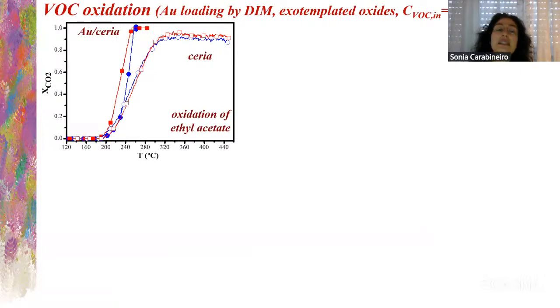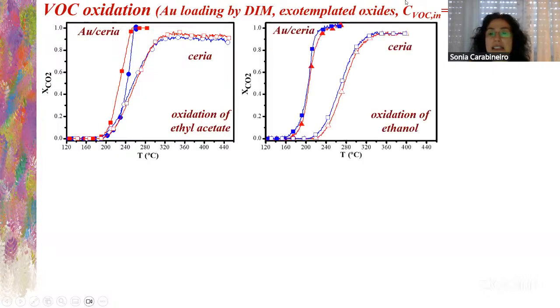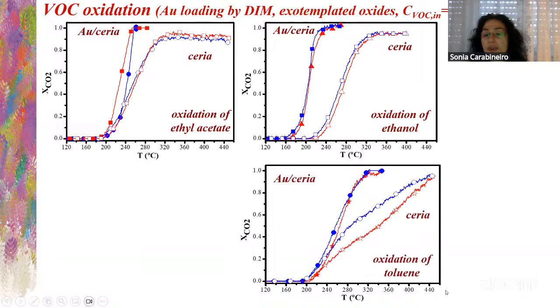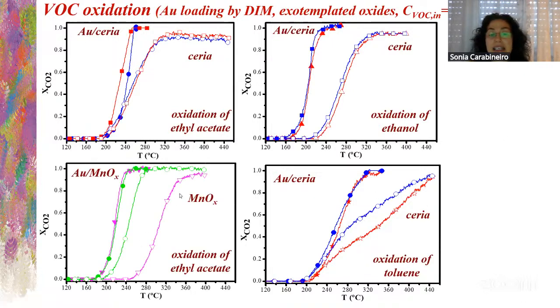And finally, with VOC oxidation using gold, okay, materials with and without gold. So here we see that adding gold, the activity improves, okay? The oxidation of ethyl acetate, okay? Here, the oxidation of ethanol, the same, adding gold improves. Here, this is for toluene, okay? Toluene is the most difficult VOC to oxidize, so it needs higher temperatures, okay? And here it's for manganese oxide samples. Again, if we add gold, it is better.